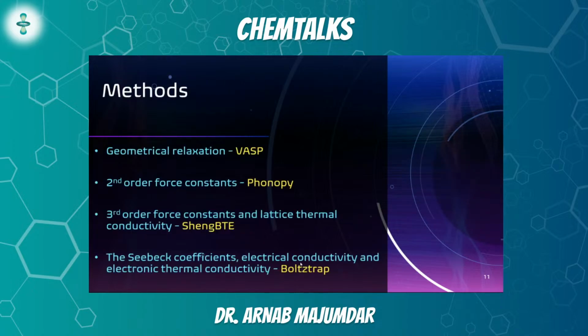The last slide before I start discussing my material is the methods in which we actually did all these calculations. The geometrical relaxations and the optimizations were done using VASP. The second order force constants and the phonons were calculated using phonopy. The third order force constants and the lattice thermal conductivity were calculated using ShengBTE. This is a Boltzmann transport equation solver. And finally, the electrical transport properties like the Seebeck coefficient, the electrical conductivity, and the electronic thermal conductivity were all calculated using this code called BoltzTraP. So it was a combination of quite a few codes that gave us the final results.